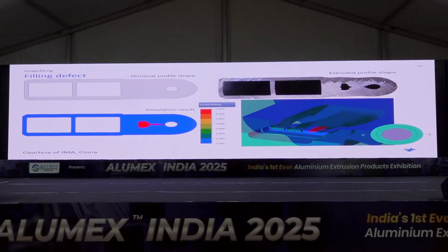Okay, so here there are two solutions. You can try to optimize the tool just based on the opinion of the die corrector, but if you do the correction of the bridge in that sense, you can make the stability of the process too bad, you can even break the tool. That's why during the optimization it's very good to check it beforehand using simulation software before you modify the tool and break it.